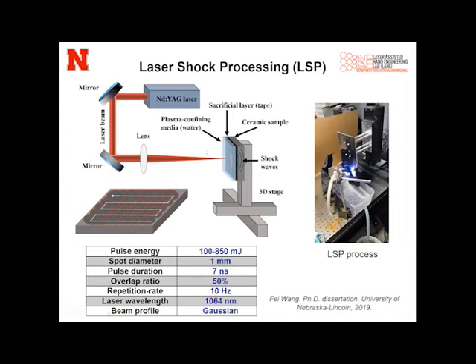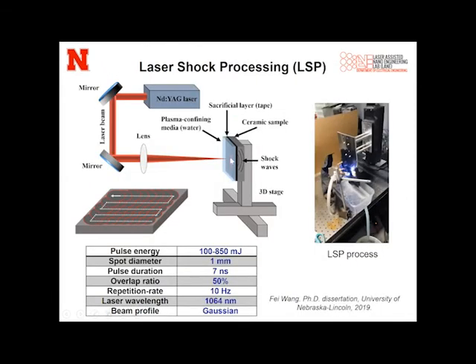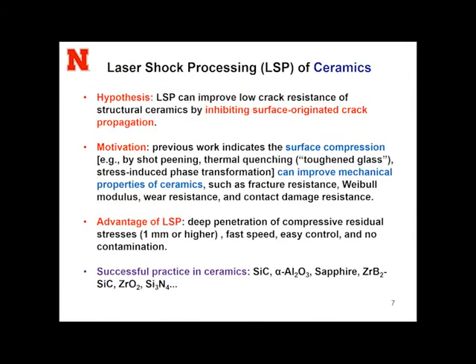At Nebraska, our lab developed our own LaserShock peening system. This is a lab size system. We use an Nd:YAG laser with nanosecond pulse duration, and we have our setup here for peening of the sample on a three-dimensional stage. So we control the scanning of the laser beam for LaserShock peening of a large area, or even some curved surface. The hypothesis here is that the compressive residual stress generated by LaserShock peening can improve the cracking resistance of ceramics because it can inhibit crack propagation on the surface.